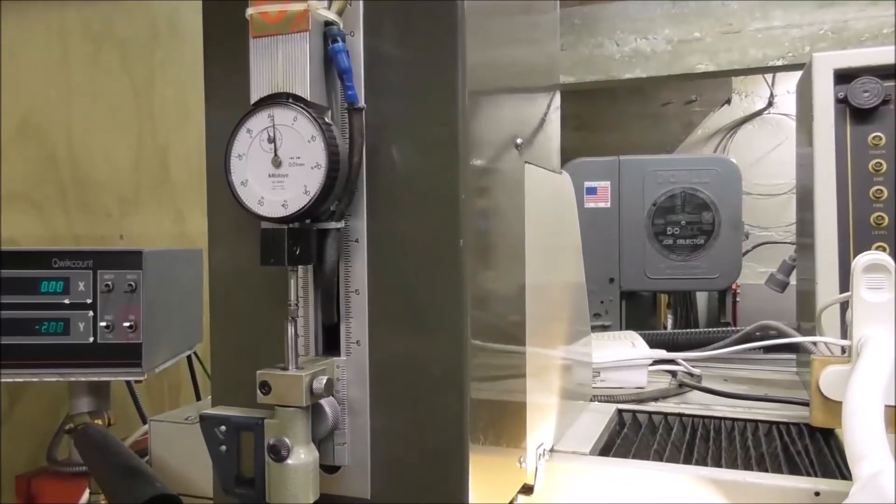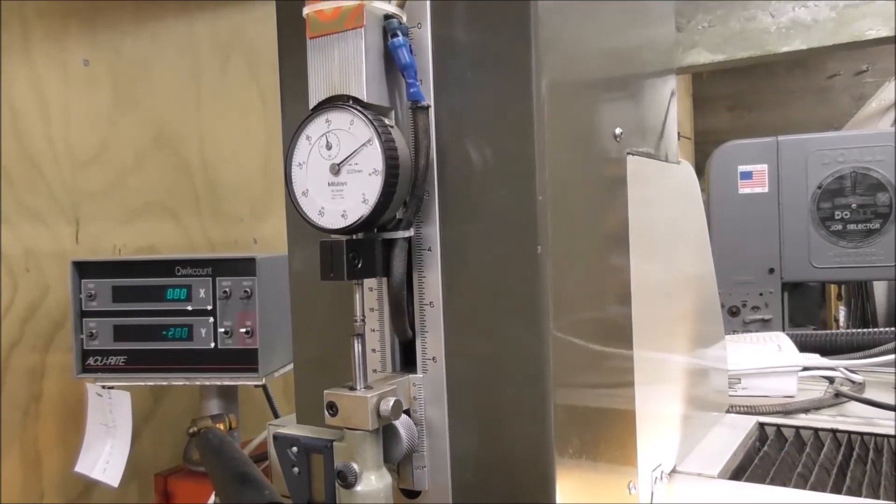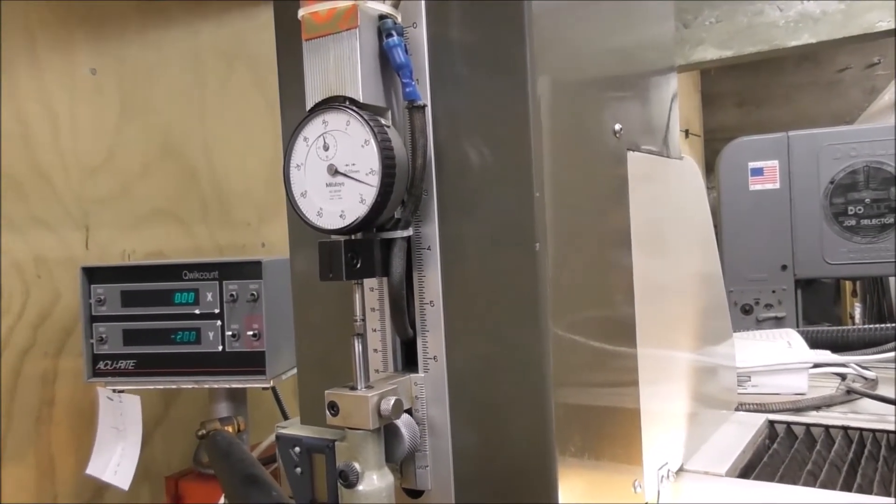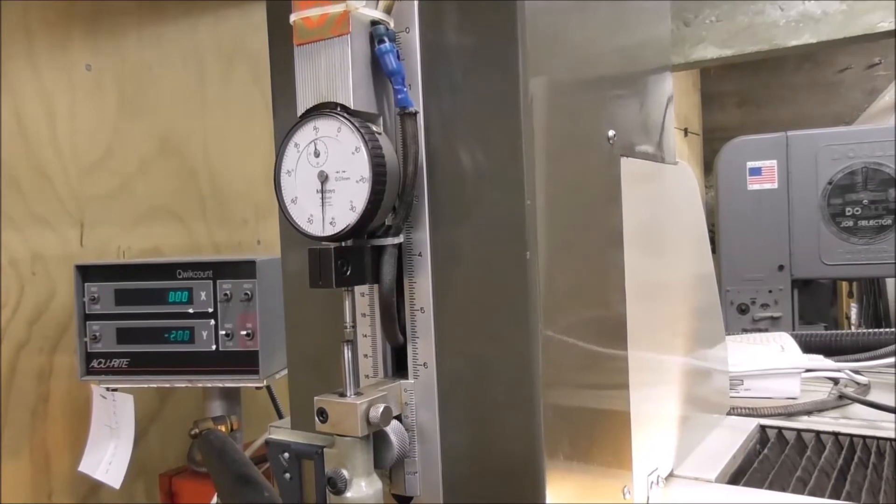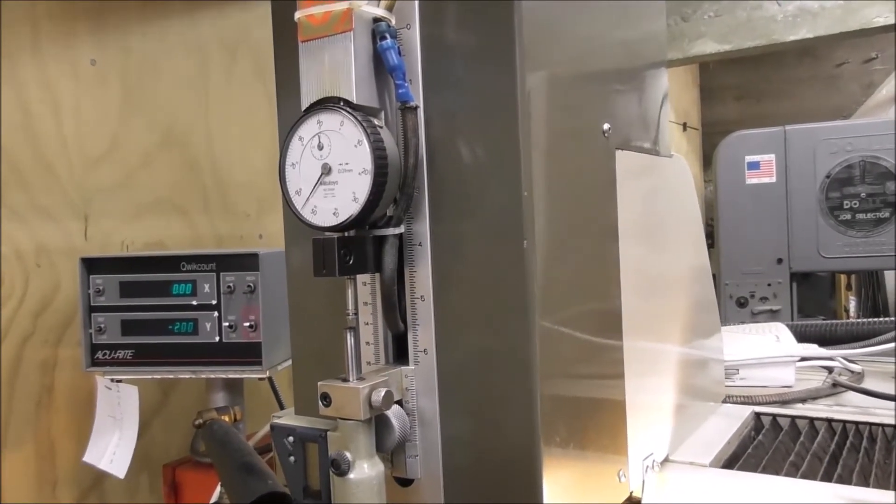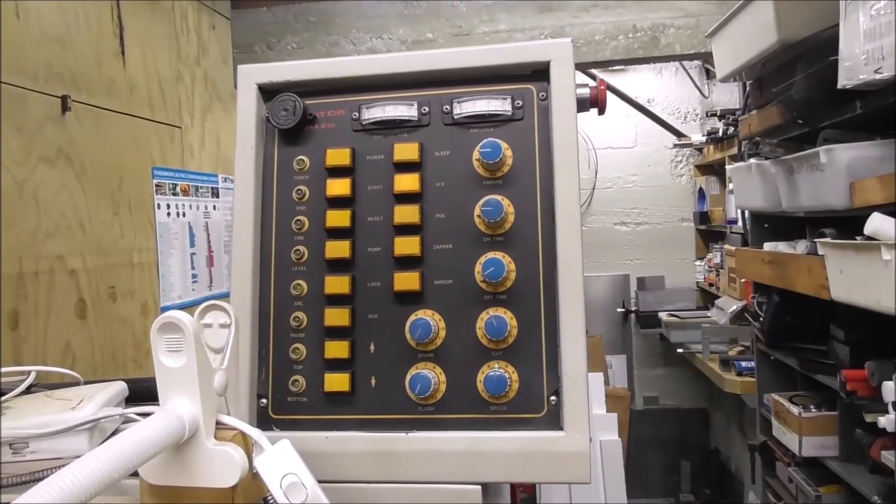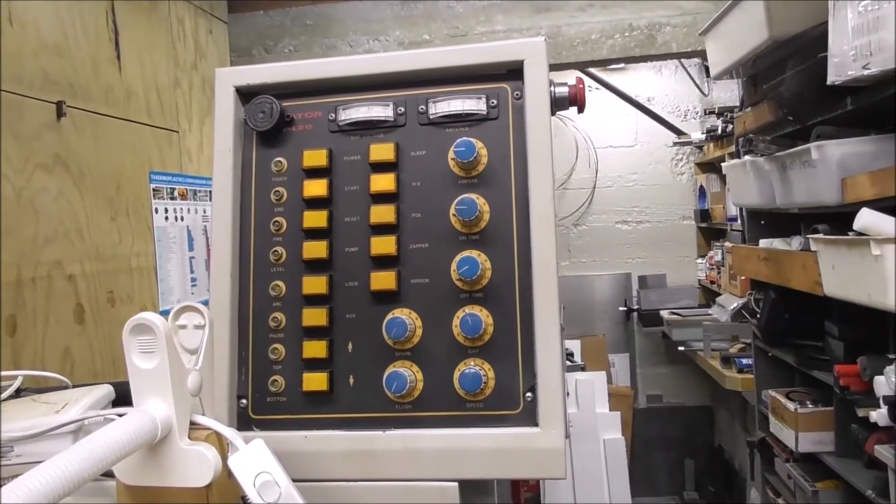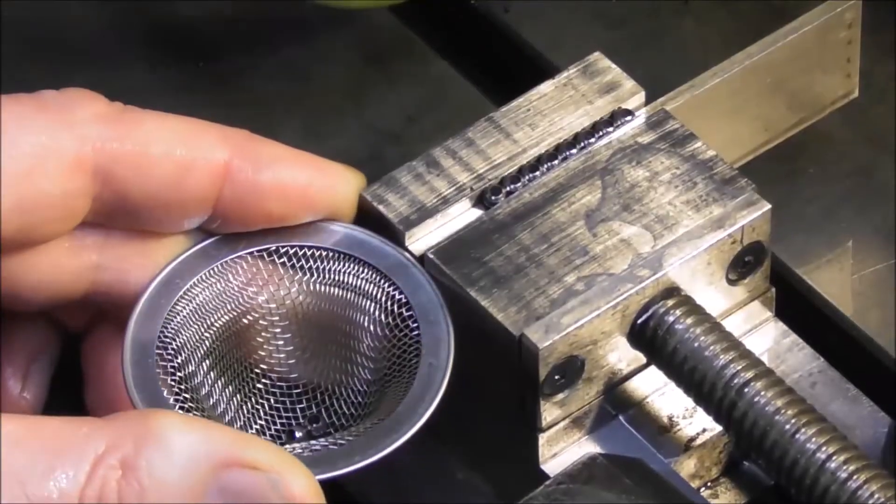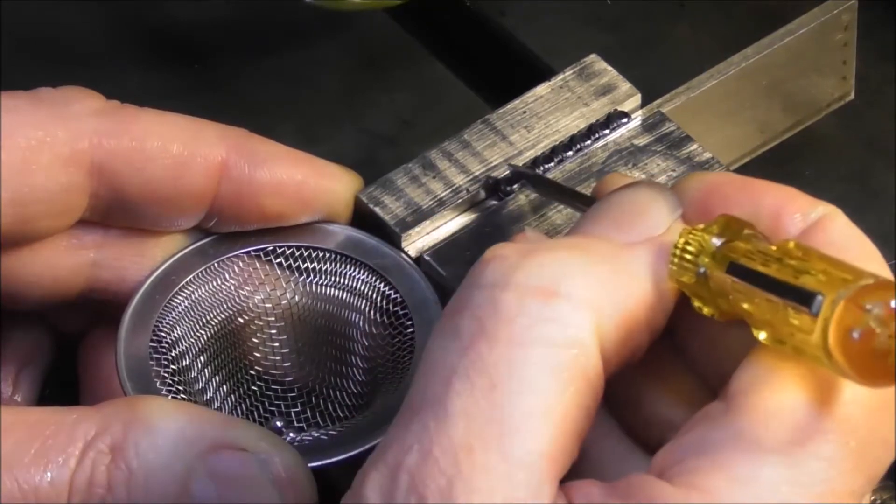I tried drilling these steel balls with tungsten carbide and cubic boron nitride and well the progress was very slow. I did manage to drill one steel ball but by the end of that the drill was getting blunt and I realized that it's quicker to spark erode it. But you know if you just need to make one then it could be a good option I suppose. These look like tiny little parts if you're not used to this type of work.